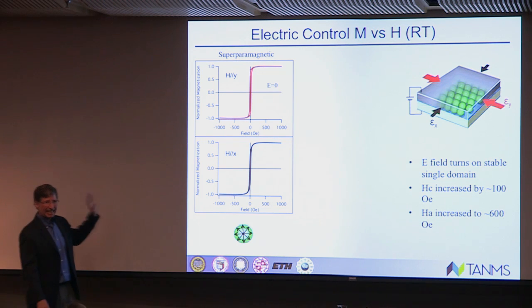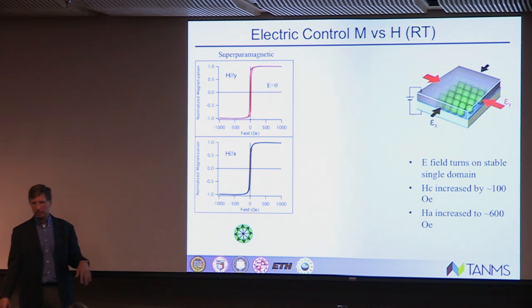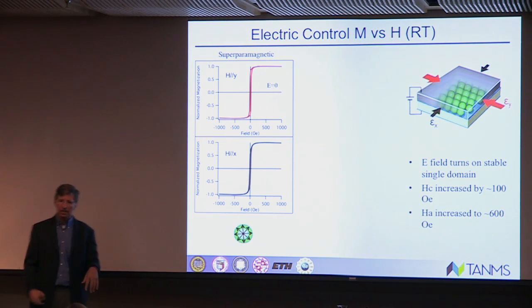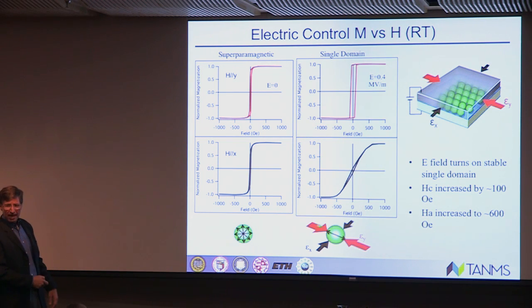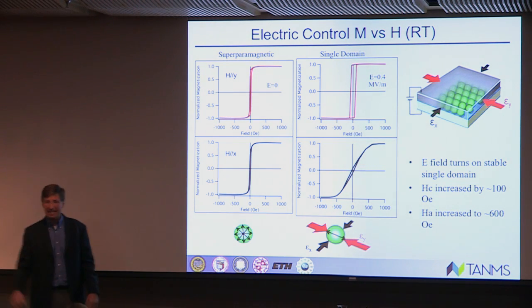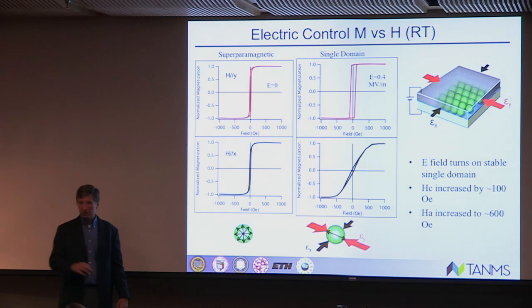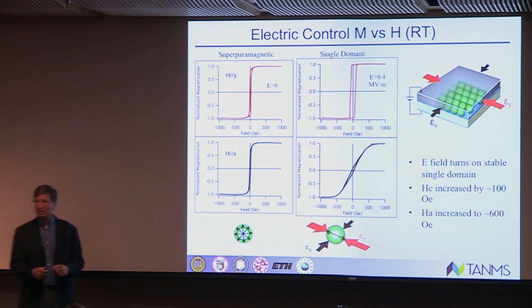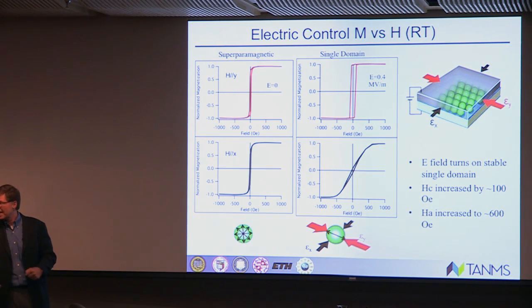Now let's take that same sample but apply an electric field to it. Not change the temperature, and let's look at the MH curves again. So by the way, this is an anisotropic cut, so you actually have a large compressive strain in this direction. The other thing is nickel is negative magnetostrictive. So if you compress it, the domain should align with that compressive strain. Lo and behold, we got something that looks single domain.